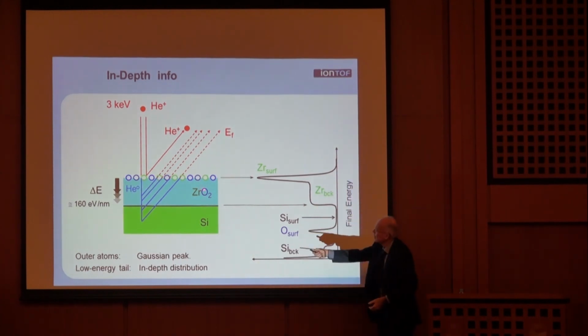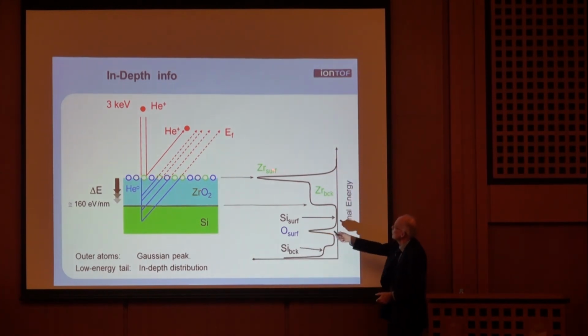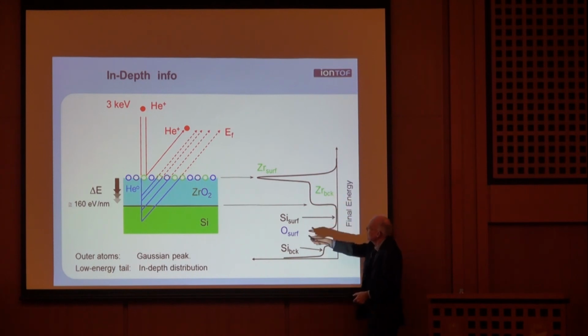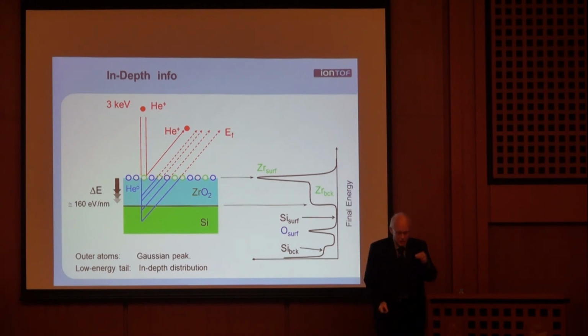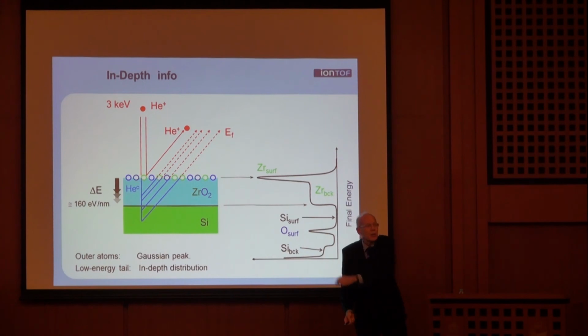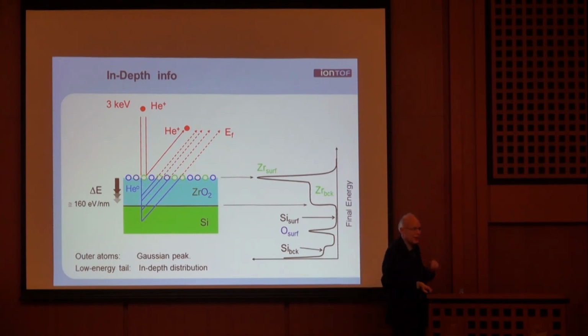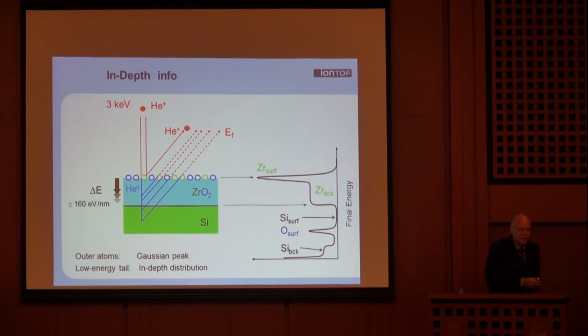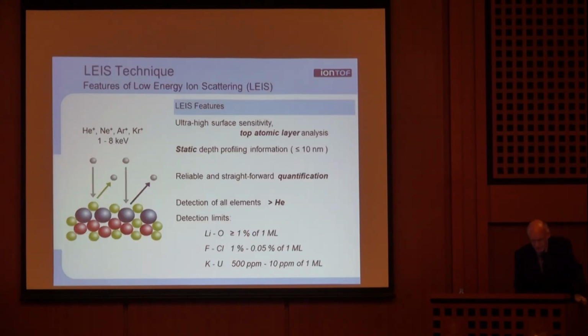And so when I scatter from zirconia, I have a surface peak, which is the top layer. And then the background, this tail, tells me how thick that zirconium layer is. It's just a friction force going whoop, whoop, whoop in, lose some energy on the way in and out, and it tells me how thick it is. And in the range of a few nanometers, we are extremely accurate in determining the thickness.